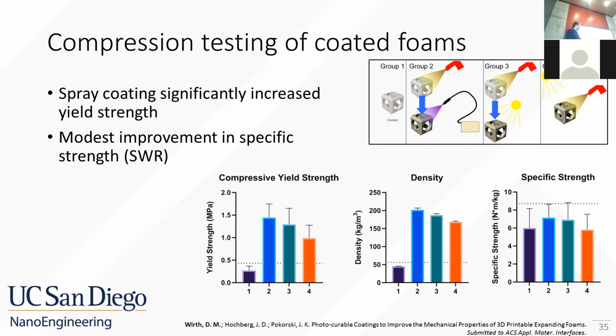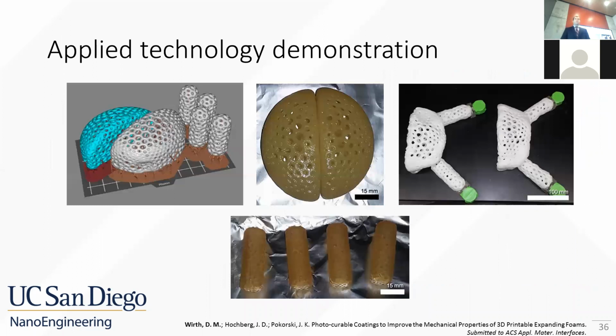Unfortunately, the density also increased once these sample cubes are sprayed, so the overall strength-to-weight ratio, or specific strength, there's not much difference. There's about a 20% improvement for groups 2 and 3 in specific strength, which is still relatively significant, but a lot lower than the improvement in compressive yield strength, which is between 330 to 430% improvement. So using this new method, using this new high strength resin, we can begin to create functional structures.